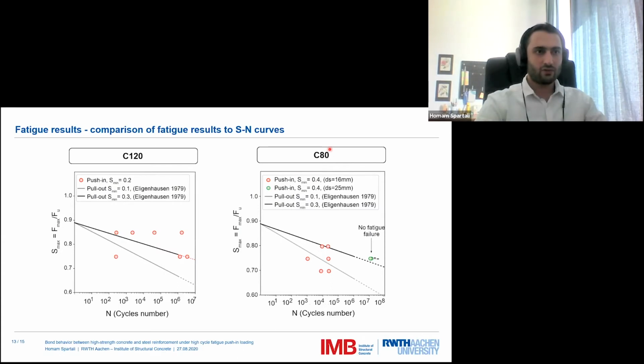And here are the results for the concrete C80. We tested here 3 load levels, and 2 of our experiments from the load level 75 did more than 10 million load cycles without failure.